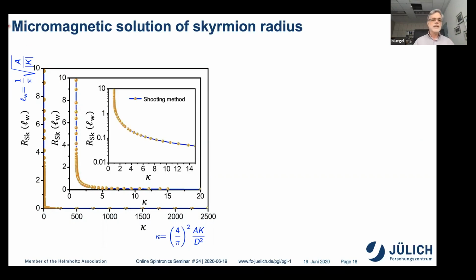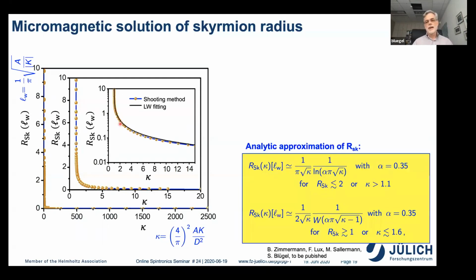And here is a logarithmic plot to see a little bit more how this function looks. So it's a function which is rather nice, but suddenly it goes up. And more or less accidentally, not fully accidentally, but by luck, I would say, we found an analytic expression for the skyrmion radius, which is related to this kappa, the logarithm of the kappa, and the root of the kappa. And this analytic function is good for kappa smaller than 2.